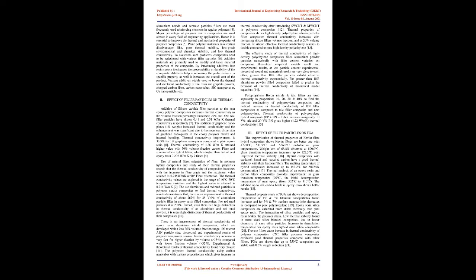8. Thermal conductivity of 1.86 W/mK was attained with 30% volume fraction carbon fiber and silicon carbide hybrid fillers, which is 9 times higher than that of neat epoxy resin, 0.202 W/mK. 9. Use of natural fiber orientation in polymer hybrid composites and study of their thermal properties reveals that the thermal conductivity of composites increases with the increase in fiber angle and the maximum value attained is 0.215 W/mK at 90° fiber orientation.